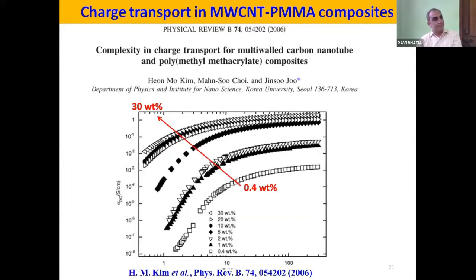Okay, so I would spend a little time on this slide, which is again the motivation for the further work to be presented here. Kim et al. prepared so many samples from 0.4 weight% to 30 weight%. Here, the 0.4 weight% sample presents the percolation threshold, and it is understandable that as the temperature is lowered from 300 Kelvin to around 1 Kelvin, there should be an exponential decay of conductivity. This is understood very nicely. There is no problem with this, but still it leaves a question. Then what is the use of multi-wall carbon nanotubes in making composites if their intrinsic properties are not being taken care of? So this is the motivation for us to carry out further work.